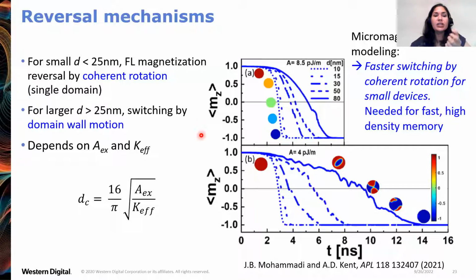For bit sizes 25 nanometers and above, the switching happens by domain wall nucleation and propagation, and that's also shown here in this micromagnetic simulation, showing that a domain wall has nucleated in the center and it propagates outward until you get total magnetization down.